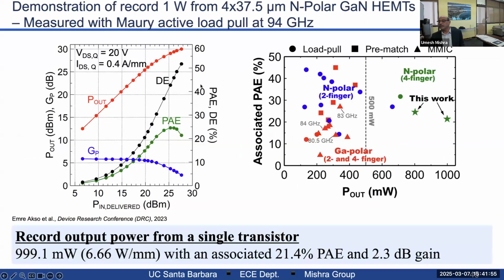Using the active load pull system, we could match the 37.5 micron device, and we got a watt at 94 gigahertz from one device. Again, if you look at the total power here, you can see gallium polar devices are here in total power. Nitrogen polar devices have again broken out of the wall in total power.